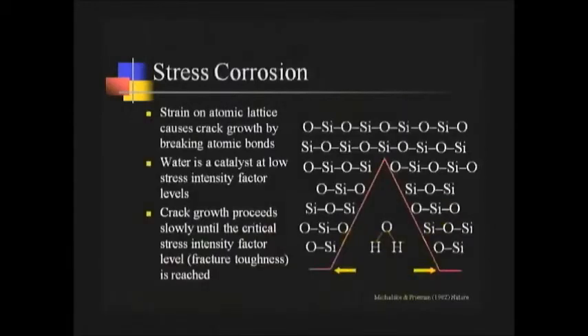Okay, so why are these cracks growing, though? We have two mechanisms for the crack growth. One is stress corrosion, and the other is cyclic fatigue. First, let's talk about what happens in stress corrosion. Usually we think about ceramic materials when we think about stress corrosion. And ceramic materials, many of them are mostly a combination of silicon and oxygen ions. So I'm representing for you here the surface of a ceramic material as a network of silicon and oxygen ions, and there is some crack in the surface there.